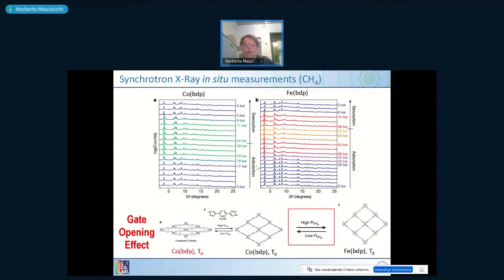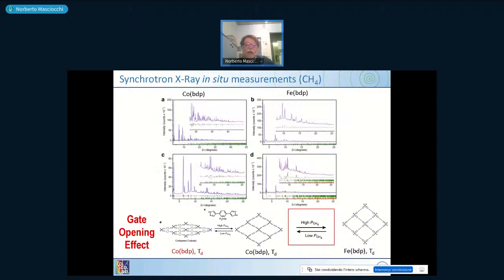So this is very important for the study of natural gas adsorption and the use of hydrogen or storage of methane in automotive. What you see here is that at low pressure, the pattern could be interpreted by the normal standard Rietveld refinement.